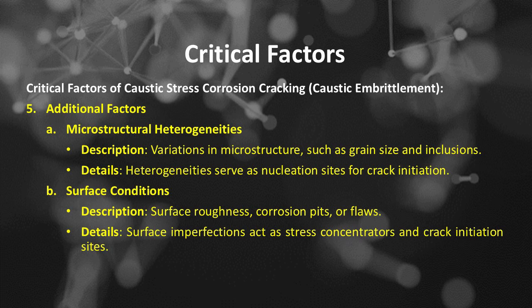Additional critical factors of caustic stress corrosion cracking or caustic embrittlement. Number A, microstructural heterogeneities: variations in microstructure, such as grain size and inclusions. Heterogeneities serve as nucleation sites for crack initiation.